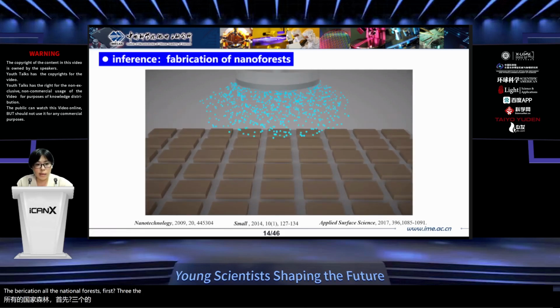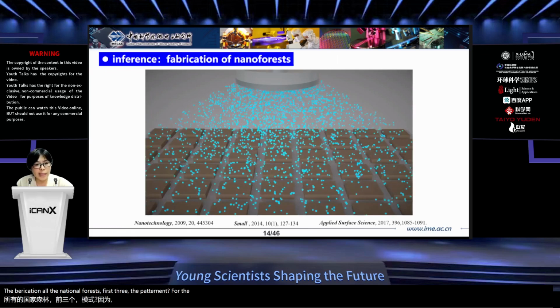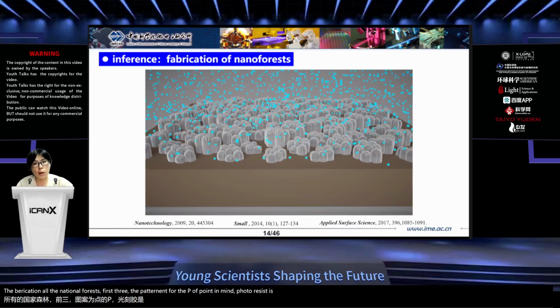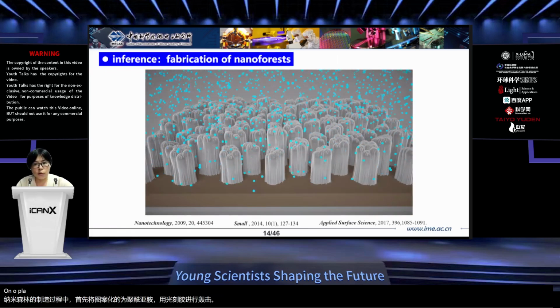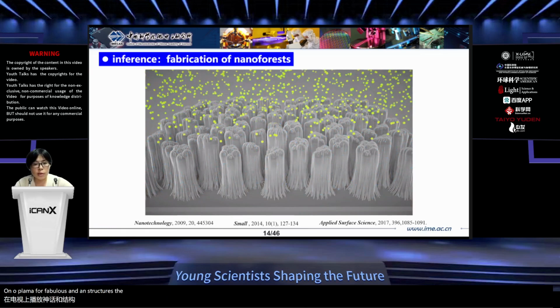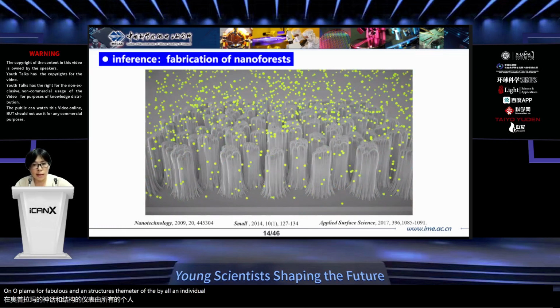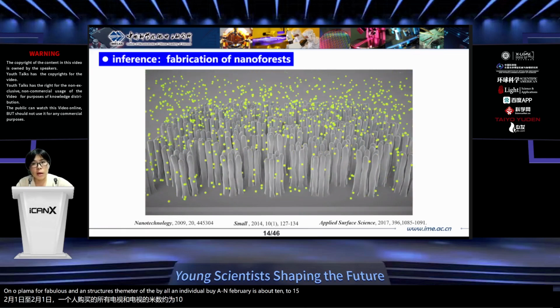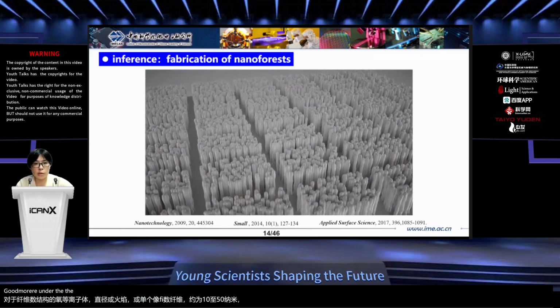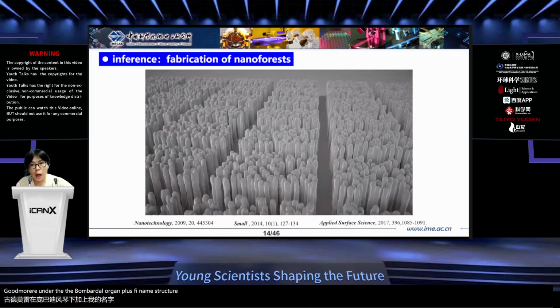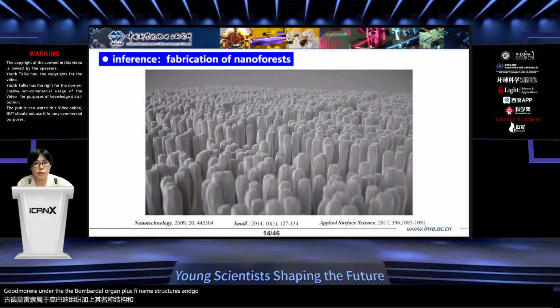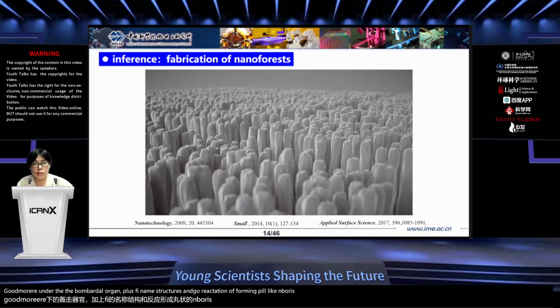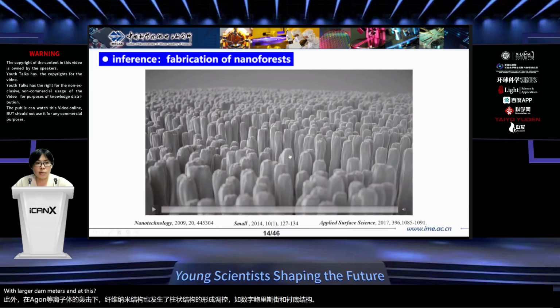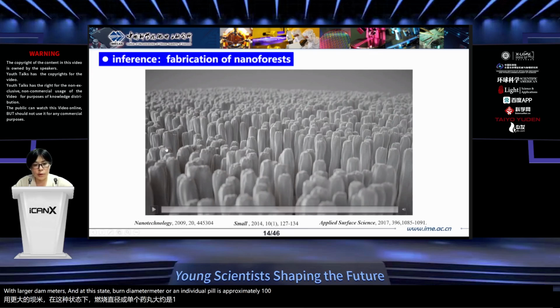Here, we will use a video to demonstrate the fabrication process of the nanoforests. Firstly, the patterned polyimide photoresist is bombarded with an oxygen plasma to form fibrous nanostructures. The diameter of an individual nanofiber is about 10 to 15 nanometers. Furthermore, under the bombardment of argon plasma, fibrous nanostructures undergo reaggregation, forming pillar-like nanoforest structures with larger diameters. At this stage, the diameter of an individual nanopillar is approximately 100 to 300 nanometers.